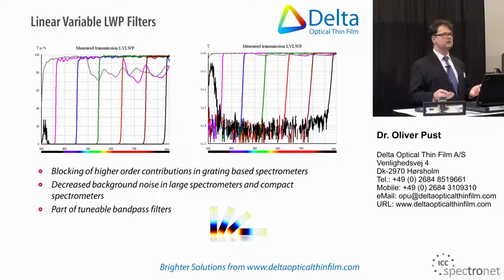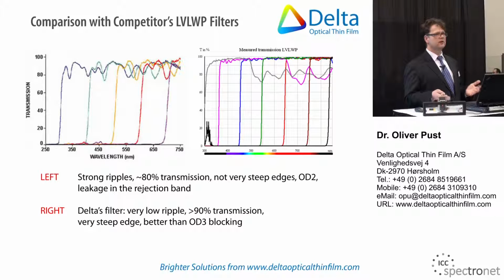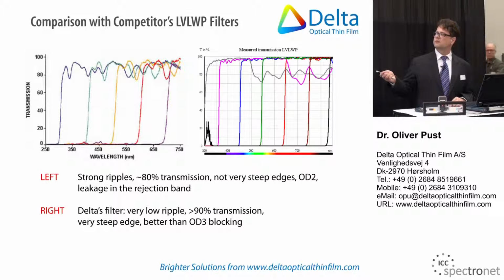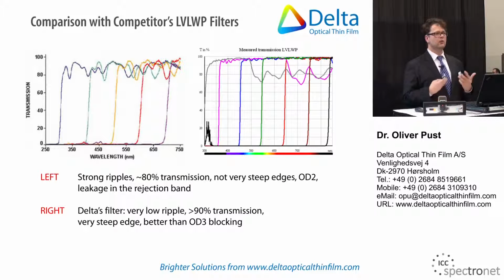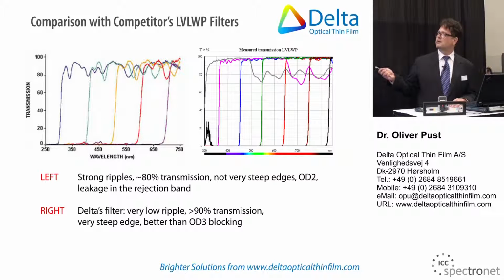Here you see a comparison with older technology that is still on the market, and here you see the obvious reason why previous technology filters cannot be used for fluorescence. It's not so much the ripple and the lower transmission level, but it's the edges which are not steep, but even worse, these leakage effects in the rejection band which render fluorescence measurements impossible with these old technology filters compared to the filters that we produce these days.